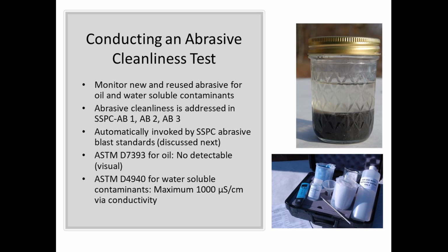We have found that a lot of folks are doing that test pretty routinely. What they're not checking the abrasive for is residual conductivity or water-soluble contamination that might be on the abrasive, because we remove a coating material or a lining material, and in the process we've contaminated our abrasive. And if we're going to reuse that abrasive over and over again, we could potentially contaminate even clean surfaces. So there's an ASTM test for that. It's ASTM D4940, and we take a known volume of abrasive and a known volume of distilled or deionized water and combine them and do an extraction. Then we filter off that water and measure the conductivity of the extract, not of the abrasive itself, but whatever came off the abrasive and solubilized in the water. A kit that has all the equipment to do that is shown on the bottom there.